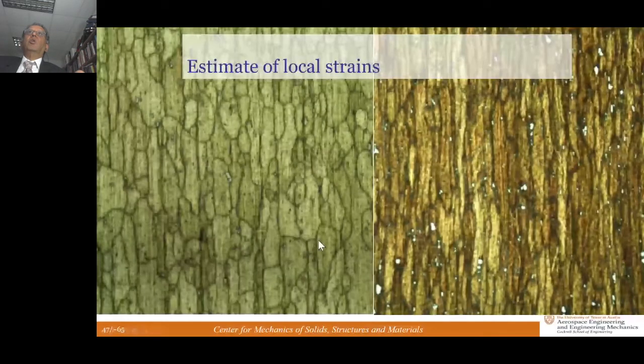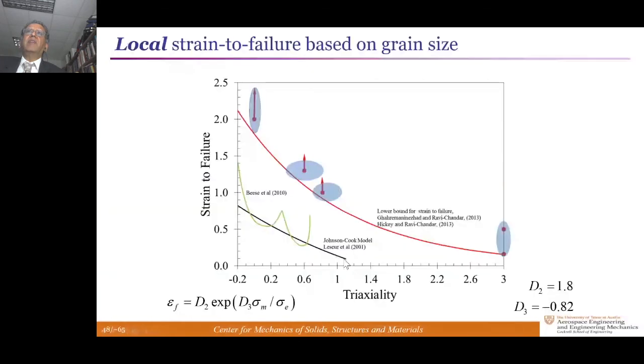Corresponding measurements for the aluminum alloy: grain structure prior to deformation, grain structure after deformation, and you can see strain levels are on the order of 1 to 1.5. Again, globally calibrated strain to failure criterion, locally calibrated strain to failure criterion. These seem to work very well and in a predictive manner.